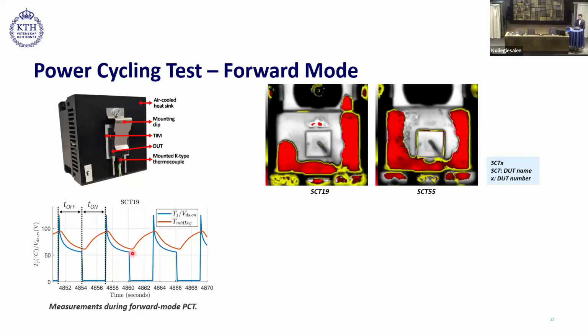Here we are looking at the scanning acoustic microscopy images of 2 of the degraded devices. The SCT in the device terminology basically represents the DUT name, and the numbers here represent the DUT number. We tested around 80 to 90 devices. That's why we used this 19 and 55 from the test database. The red region here represents the delaminated area. We should focus more towards the die, which is represented in this region. So in SCT19, we don't see any delamination. However, in SCT55, partial delamination at the edges is observed.